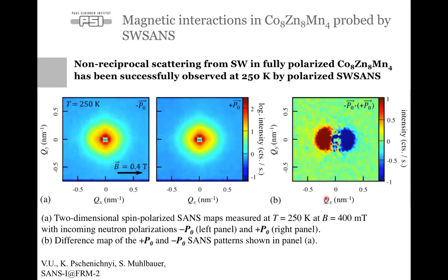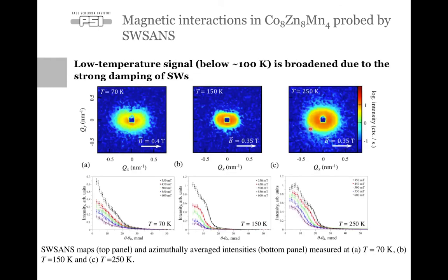And we used the same technique to probe the exchange stiffness in cobalt zinc manganese 884. And we could again observe this asymmetric distribution of spin wave scattering intensity, suggesting that we really have the non-reciprocal propagation of the helimagnetic magnons in this material, which is not surprising because it has the chiral magnetic structure and also DMI. And we have measured the temperature dependence of this spin wave scattering pattern.